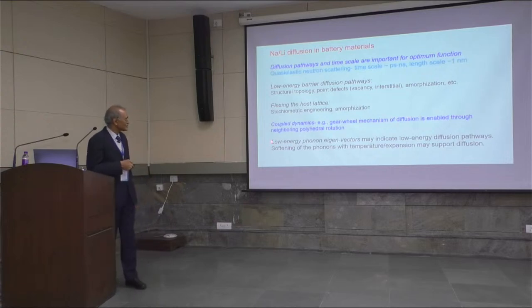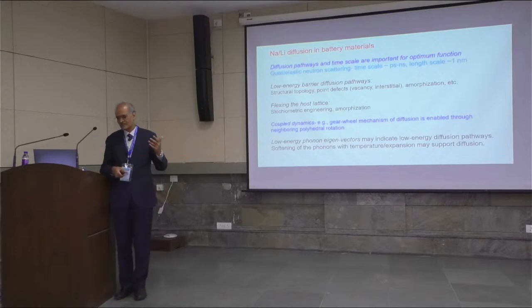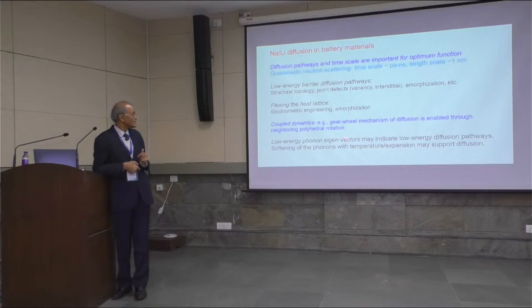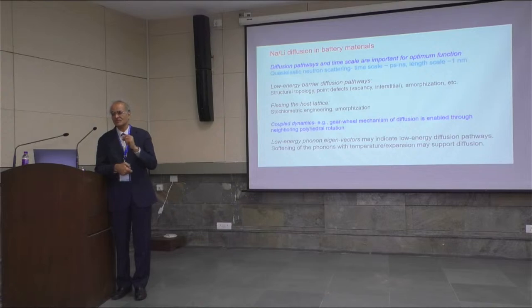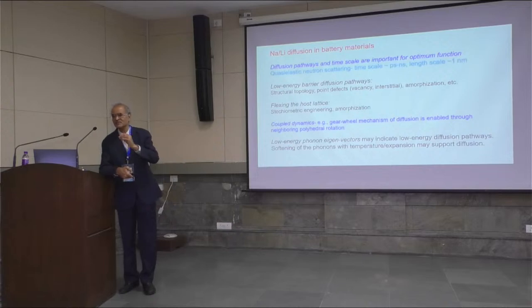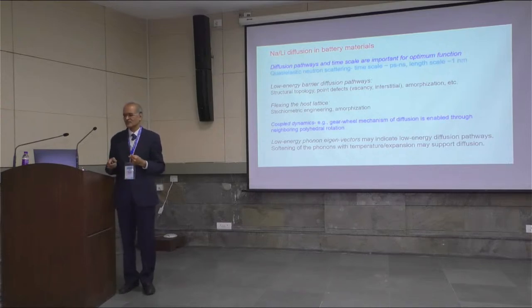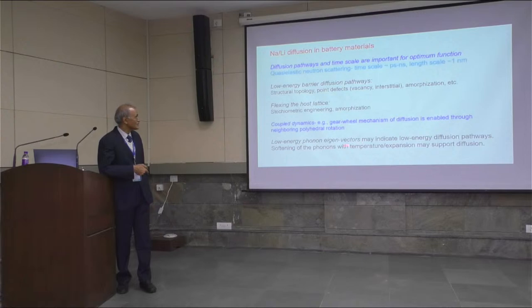Then it is also common that you have low energy phonons in different structures. Depending on how the structure is engineered, you may find that there are very low energy phonons associated with the diffusing atom, lithium or sodium atom. As I said, it's not a liquid-like diffusion. For most of the time, the atoms are located at definite sites and they jump over from site to site. And that is how the ionic conduction or diffusion takes place. So, low energy phonons, and the eigenvector of these phonons may be related to the low energy diffusion pathways.